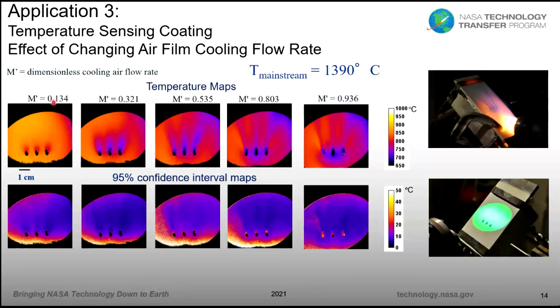And as we increase that flow, I should say in the burner, the mainstream gas temperature is 1390 C. So as we increase the flow, you can see the extent of the air jet cooling becomes greater, especially in length. It covers a longer and longer distance, a little bit bigger area. But very interestingly, as we continue to increase the cooling airflow, the cooling becomes much less distinct. You actually lose cooling effectiveness as you keep going up in the cooling air flow. And that's due to a well-known phenomenon that air jets coming out of these holes, if they get too fast, will lift off the surface and no longer effectively cool the surface.